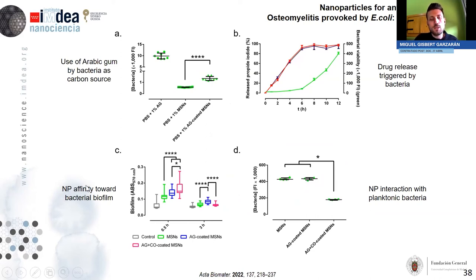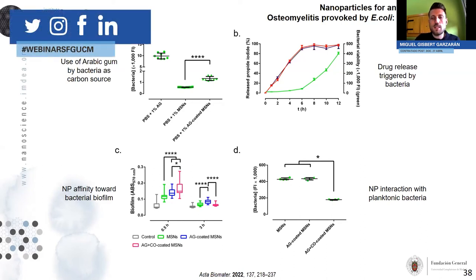This is very interesting because we could observe that, look at the blue one, please. In the case of nanoparticles coated with Arabic gum, we observed that there was a statistically significant increase of the amount of nanoparticles retained on the bacterial biofilm. And this is important because, in the case of cancer treatment, we said that nanoparticles can be administered intravenously because they accumulate in the tumor due to this EPR effect.